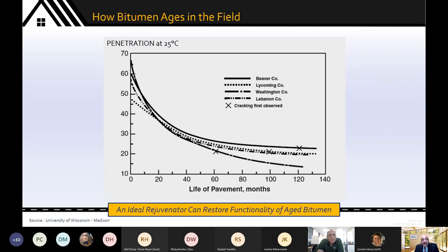So how does bitumen age in the field? Courtesy University of Wisconsin. They extracted cores from different roadways as a function of life of pavement and looked at penetration. This is how it ages. Penetration is one value. You can use other tests like low temperature properties. You can use other tests like LAS fatigue. They all will show roughly the same decay, Arrhenius type decay, simplistically speaking, in properties as a function of time. So this is what you're looking to remedy. This is what you're looking to rectify.